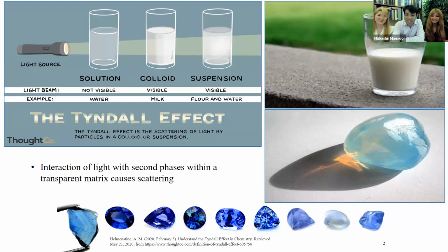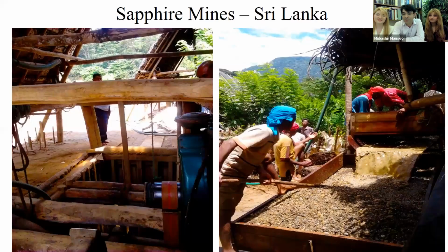Yeah, and this is important to analyze because a lot of sapphires that come from Sri Lanka or from Madagascar have a very similar kind of a milky appearance to them. So basically, the reason why they use the term milky sapphires is due to the same analogy. So sapphire in itself should be very transparent, but we just mentioned there could be secondary particles inside. And those secondary particles tend to create this milky appearance that is very common.